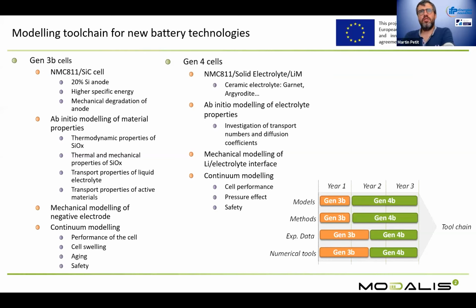And then once this first development on the Gen 3B is in motion, we will switch to Gen 4 cells in order to specifically analyze the behavior of the solid electrolyte and the interface between the solid electrolyte and the lithium metal. Several electrolytes will be studied in this project in order to get some generic approaches for this electrolyte modeling. So in order to get information on the behavior of the electrolyte and especially on the ionic conduction in this electrolyte, we will have some ab initio modeling of the electrolyte properties, which will investigate the transport numbers and diffusion coefficients of lithium in this electrolyte. And we'll have some dedicated mechanical modeling for the lithium electrolyte interface. And in the continuum modeling, as for the Gen 3B, we use this data in order to evaluate the cell performances, the pressure effect, and the safety of the batteries.